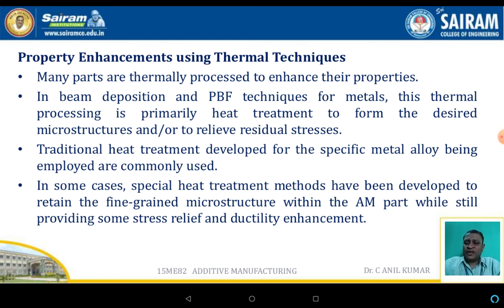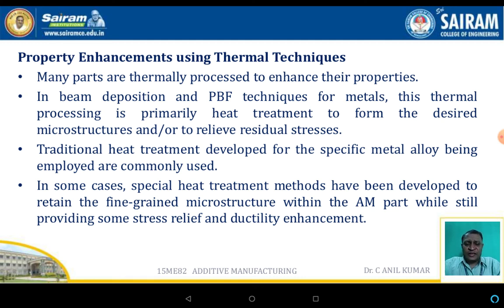Properties enhancement by thermal techniques: many parts are thermally processed to enhance their properties. In beam deposition and powder bed fusion (PBF) techniques for metals, this thermal processing is primarily heat treatment to achieve the desired microstructure and to relieve residual stresses developed in the material during the process. Traditional heat treatments developed for specific metal alloys are commonly used. In some cases, special heat treatment methods have been developed to retain fine-grained microstructures within additive manufacturing parts while still providing stress relief and ductility enhancement.